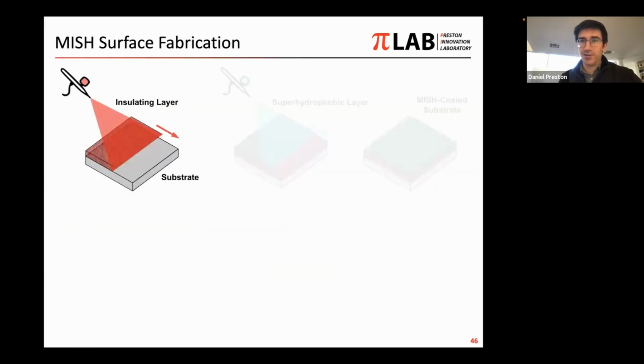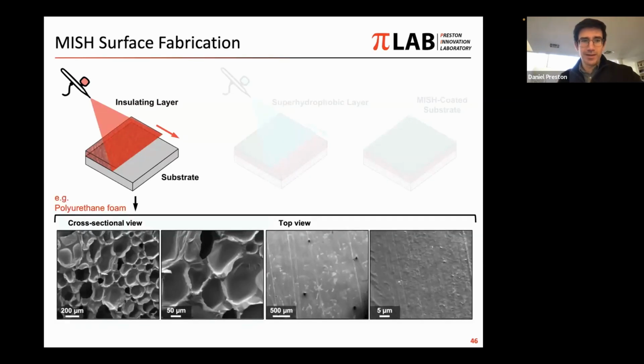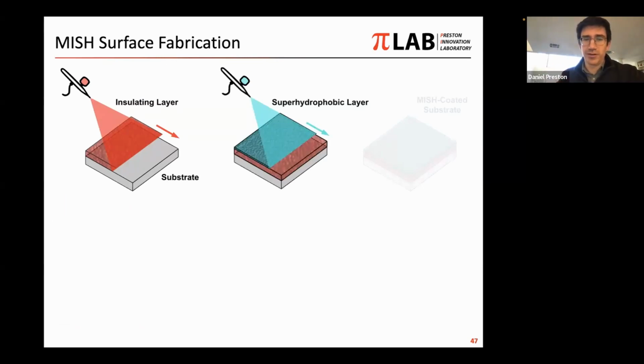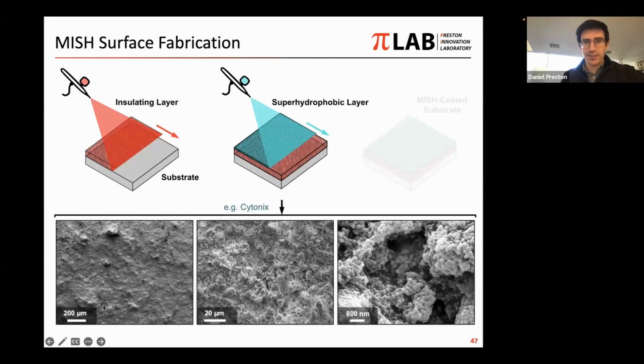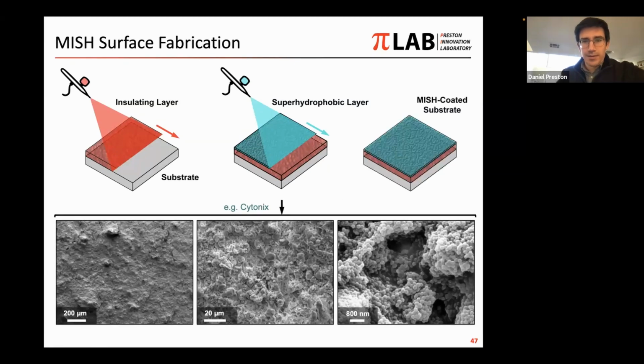And so again, this fabrication, we've decided to try to keep it quite scalable and simple. So we first spray coat with an insulating open cell foam. And in this case, it's a polyurethane foam. So we have a cross section, we cut it, and we look at the side view, and we just have these nice high void fractions in the foam. Top view shows something that looks essentially flat. So we have lots of pores inside. The top surface remains essentially flat. And then we take this and coat it with a spray-on superhydrophobic coating. And so in this case, we have some SEM images of the coating applied on top of the insulating layer. And together, these give us this MISH-coated substrate.